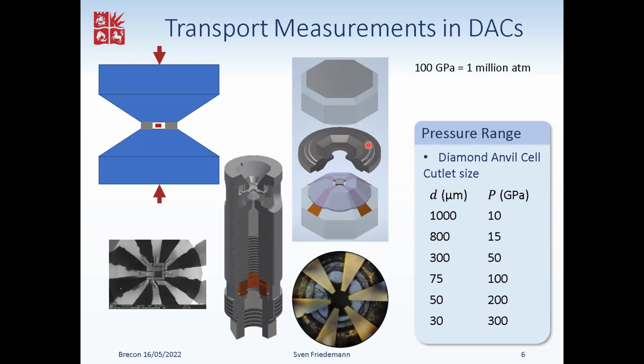And that, of course, causes the problem that this gasket sitting right on top of the electrodes would immediately short anything. That means we also need a thin, electrically insulating layer. I've sketched this here as sitting on the anvil, but in most experiments, we actually put the insulation on the gasket itself. We produce this from insulating materials. Depending on what pressure we want, we have to keep in mind at what pressure some materials might become metallic. So most of the time we use boron nitride or aluminum oxide, which stay insulating to quite high pressures.